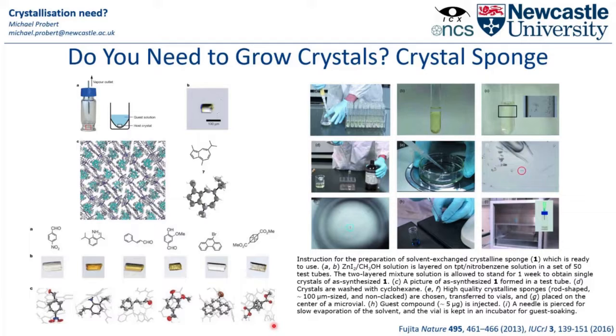Now, that is slightly problematic, but the technique is incredibly advantageous for samples where you're not able to access the solid phase under ambient conditions. So if you're a gas or a liquid under ambient conditions, then gaining a crystal is significantly more of a challenge. So I think both crystal sponge and micro-ED are techniques which we consider as parallel tools for problematic crystallization, and should definitely not be forgotten. Luckily, they're not in competition at all. These techniques are entirely complementary.